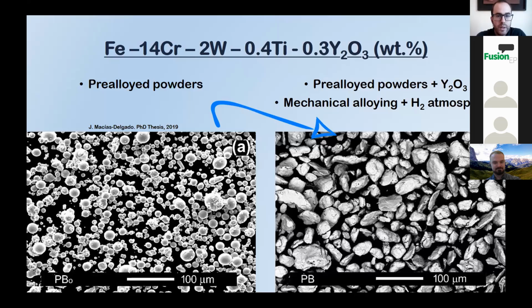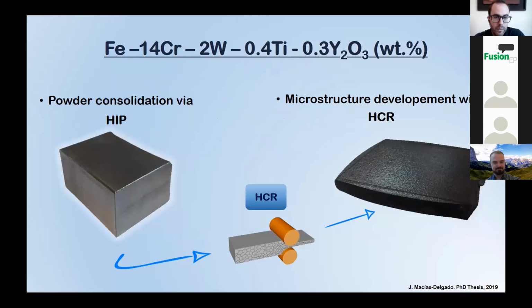Today, I will be presenting the most important results of our investigation about the characterization and thermal stability of an ODS ferritic steel. It was obtained via a powder metallurgy process from prealloyed powders and nanosized yttria powder, from which we will obtain the nanoparticle dispersion. Heat processes were performed for the powder consolidation, obtaining the first pieces of the material. Then an HCR process was performed on the consolidated materials for their microstructural development, obtaining around a 70% thickness reduction.